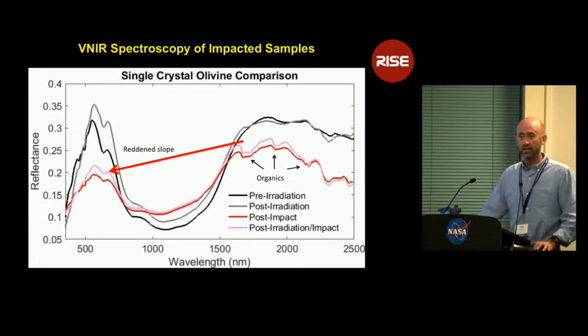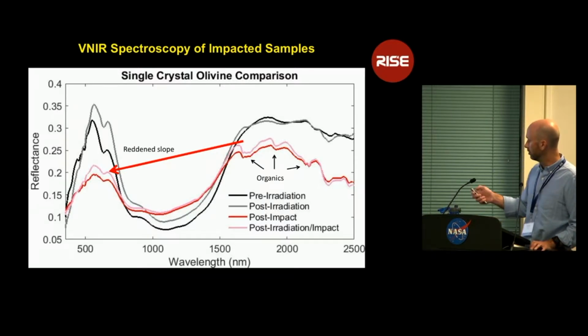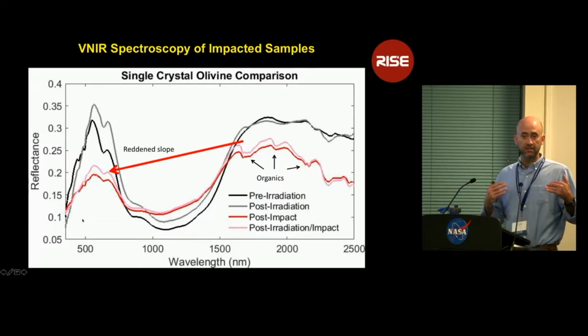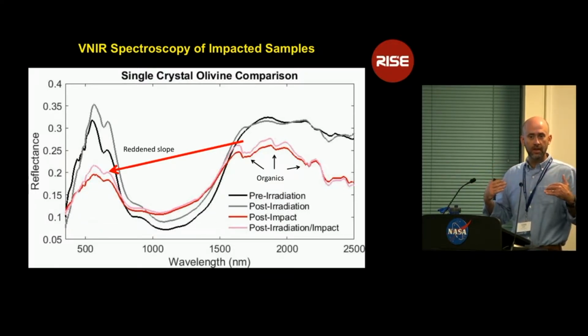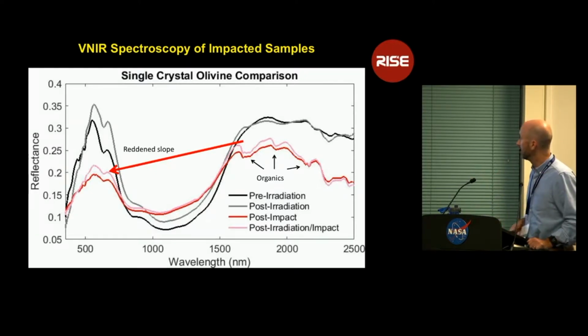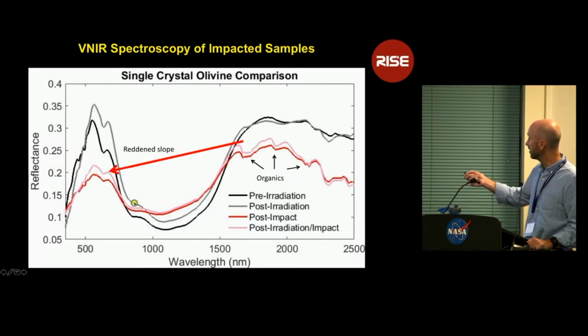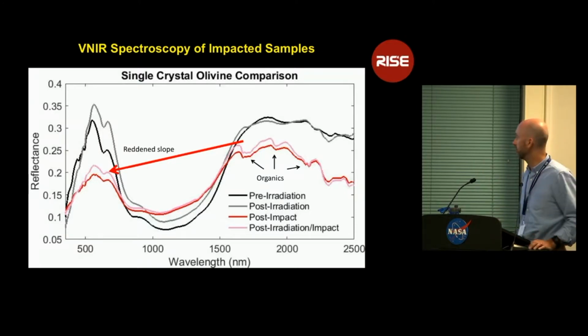space weathering process. We see an overall reddening of the slope going in this direction. We see a decrease in albedo overall, and we see a dampening of the depth of the spectral features. We also see some organic signatures in there. That's due to the coating on our projectiles, which has then become incorporated into our sample.